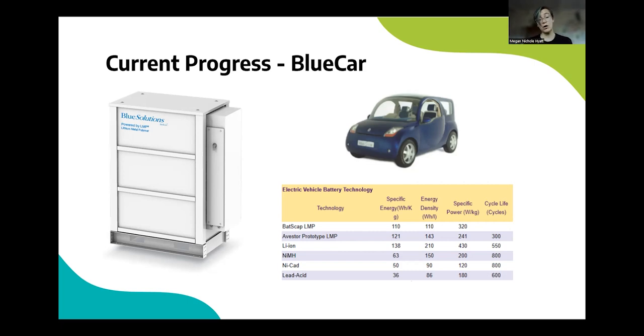To create their battery, ultra-thin layers of metallic lithium foil anode, solid polymer electrolyte, organic cathode, and aluminum foil current collector are layered, coiled, and compressed into a prismatic shape and assembled into battery cells. The vehicle itself was a small two-seater vehicle, and its battery had a capacity of 30 kilowatt hours, equating to a range of about 150 miles. Comparatively, a Tesla Model S with a liquid lithium-ion battery has a capacity of 100 kilowatt hours and a range of 400 miles, although it was developed several years later, obviously.